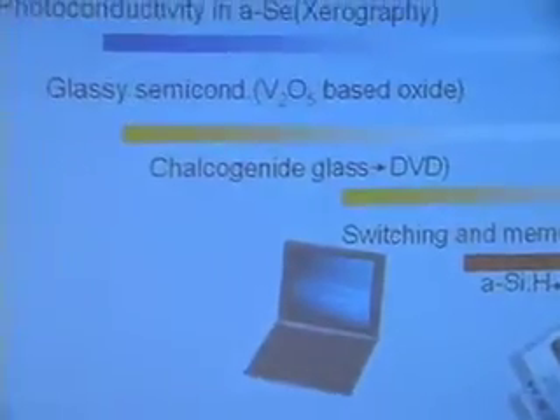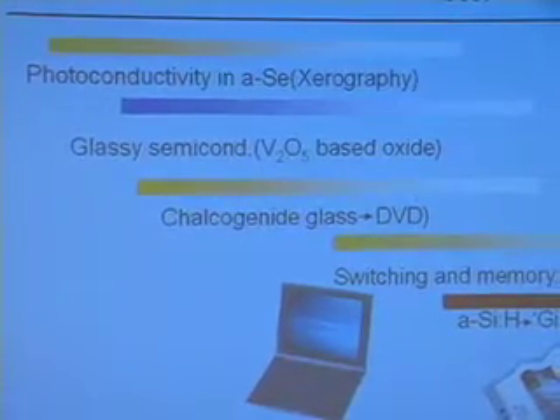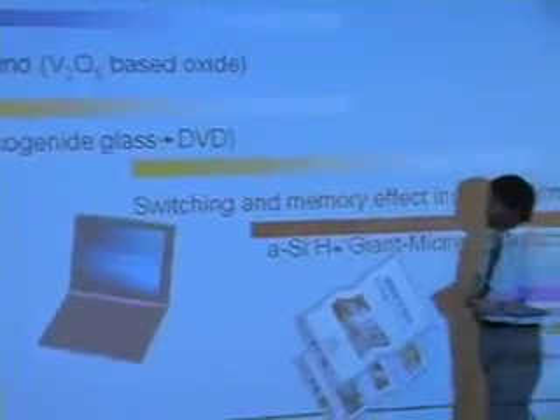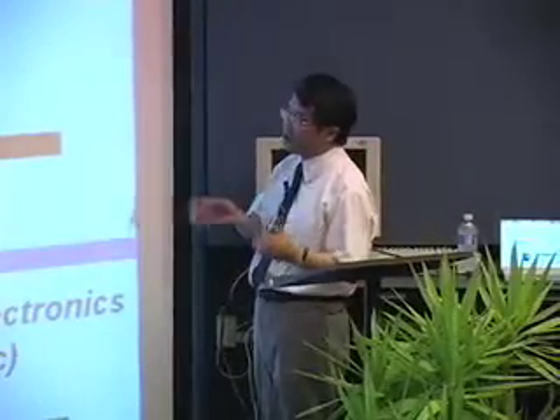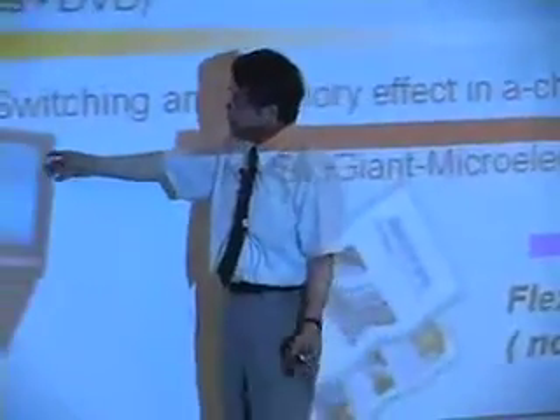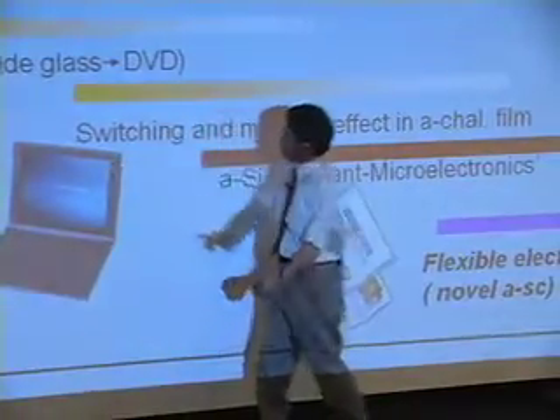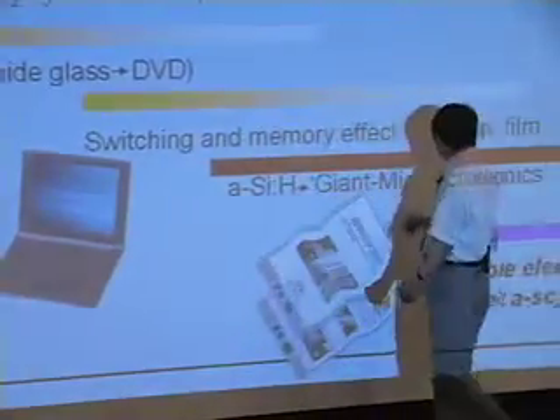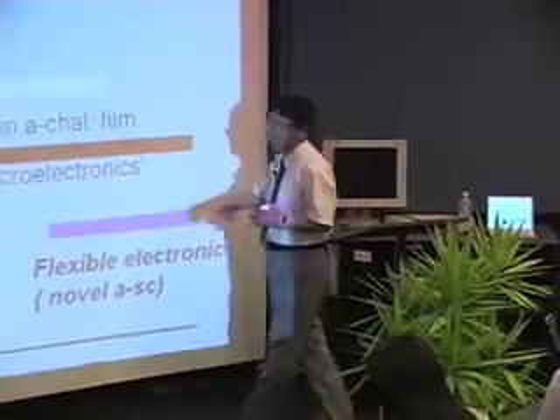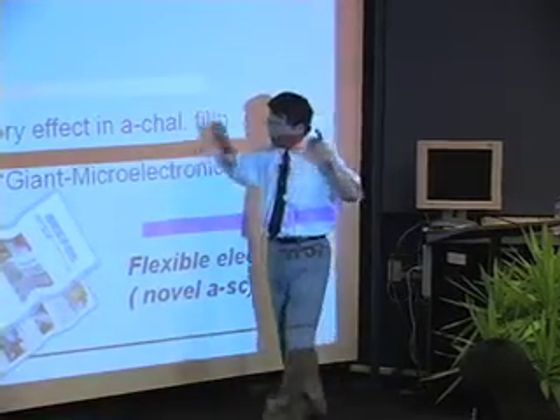But the most striking invention of the amorphous semiconductor is, of course, hydrogenated amorphous silicon, in 1975 by Spear and LeComber at Dundee University in the UK. Amorphous silicon is the first such material which can control polarity, n-type and p-type. And after that, as liquid crystal displays appeared, each pixel of the display is switched by a thin film transistor of amorphous hydrogenated silicon. The invention created a huge market of giant microelectronics. Giant means large circuits fabricated on a glass substrate.